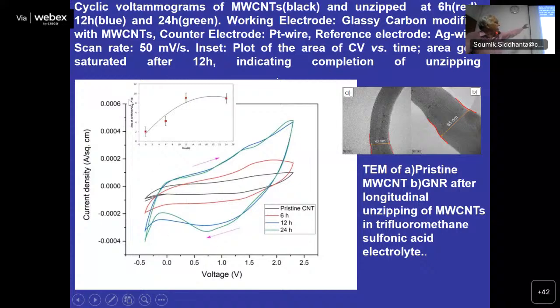So the area change with the time, if you plot, it gets saturated by this area. That means complete unzipping happens by this many hours. TEM is also revealing multi-wall carbon nanotube diameter. You can see this is a diameter. Open it out. If R is the radius of this, 2 pi R will be the diameter. Roughly a geometric correlation is seen in TEM. That's why this data is beautiful because everything is open.